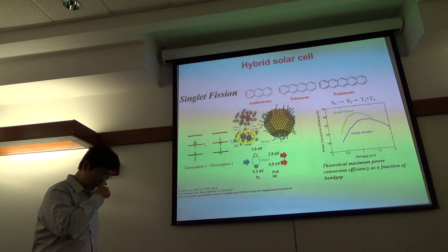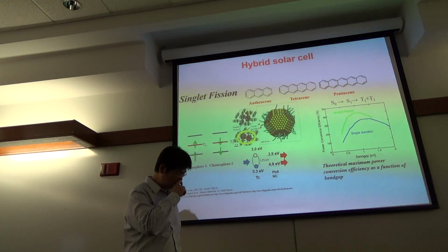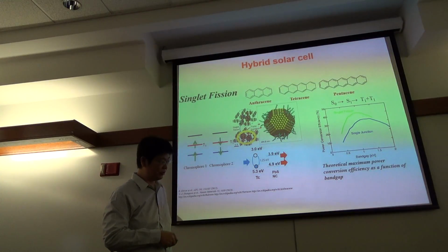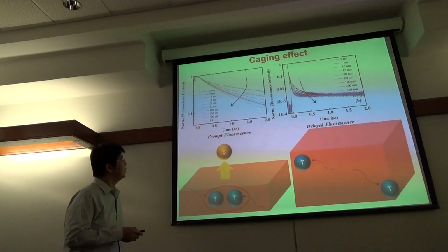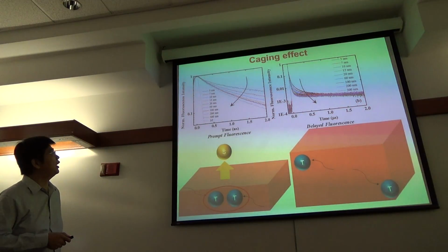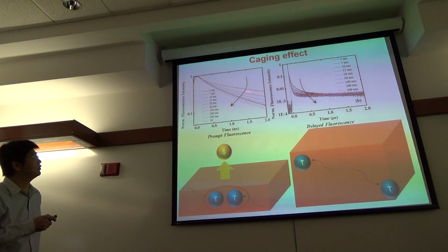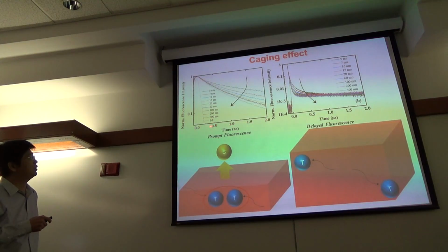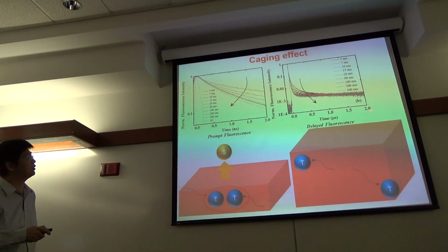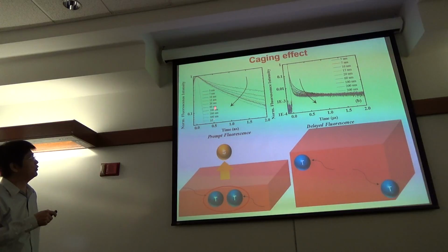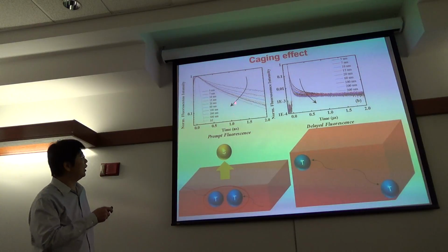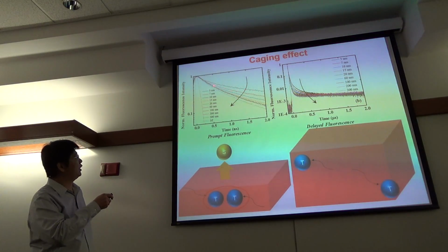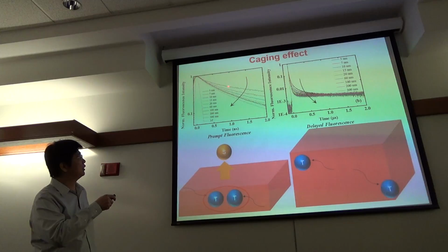Yeah. So we studied this kind of singlet fission dynamics, and especially the singlet exciton and triplet exciton. So it's the transient PL study in the 2 nanosecond range and the 2 microsecond range. So with different thickness of our organic material, we found that with the thinner one, they have the stronger signal.